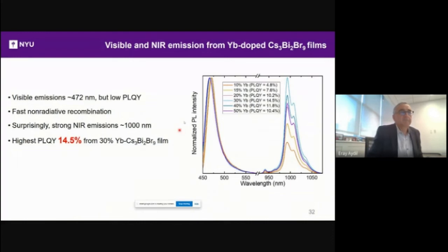And in fact, we have a highest photoluminescence quantum yield of 14.5%, which is basically the highest for any non-lead-containing material. So there's a sweet spot as you put in the ytterbium, but it drops off. And remember that I also told you that small amounts of a new phase might be appearing, as the optical absorption shows.